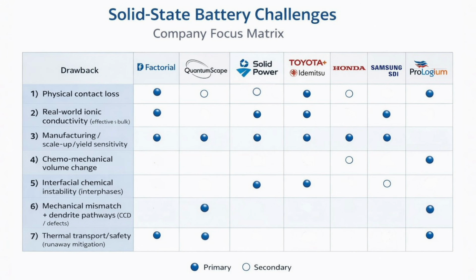QuantumScape is heavily investing in ceramic separator manufacturing for dendrite suppression and to raise the practical current limit and resist shorting pathways. Ceramic is also non-flammable, and anode-free architecture that forms lithium metal during charging can address energy density, dendrites, and architectural change. Solid Power is using a sulfide solid electrolyte for ionic conductivity.